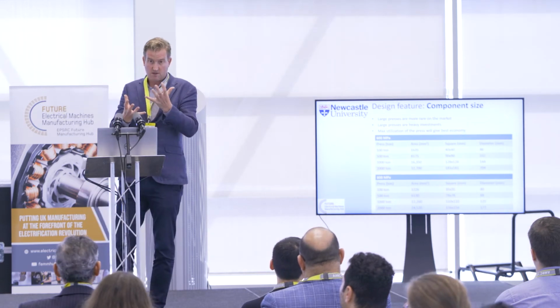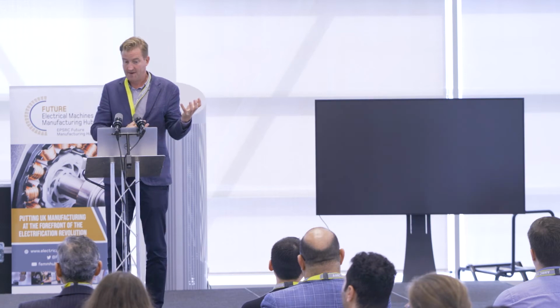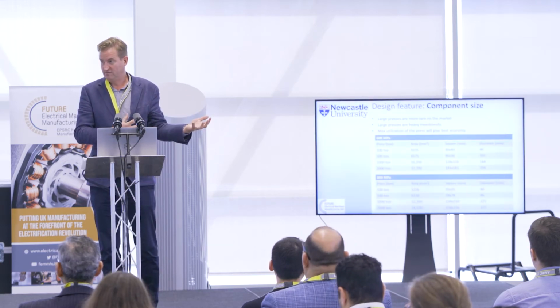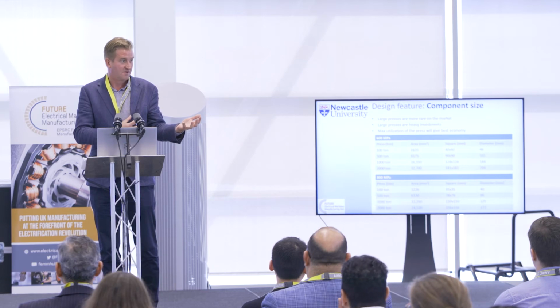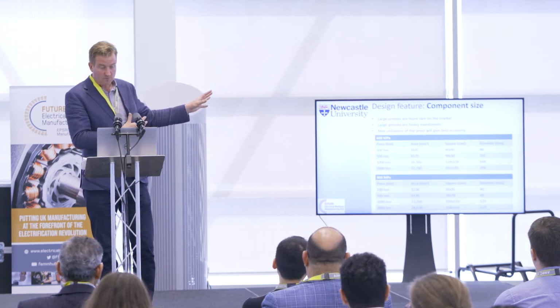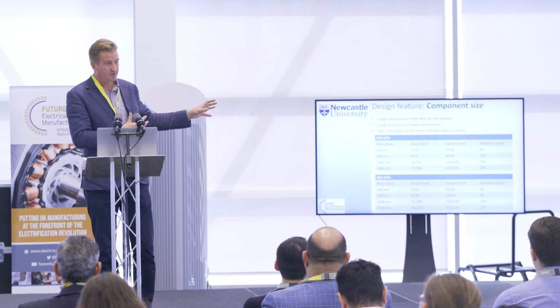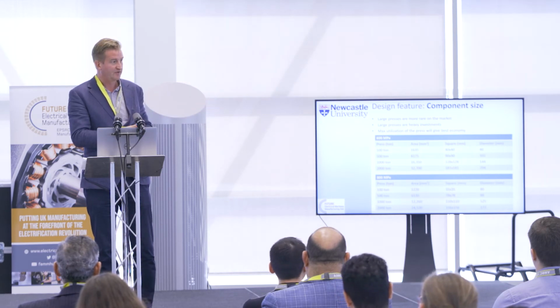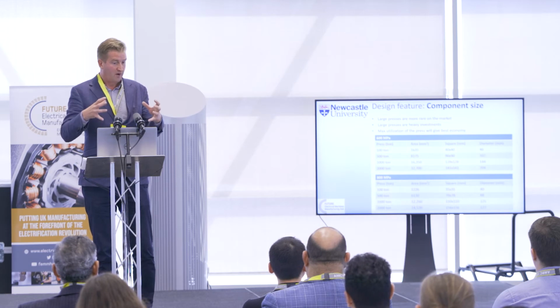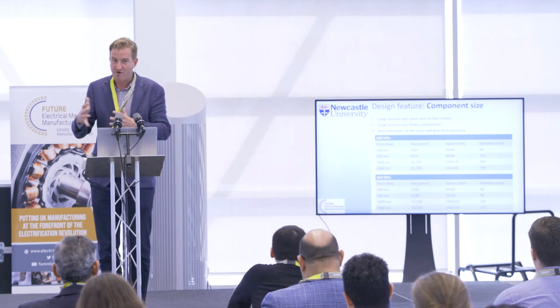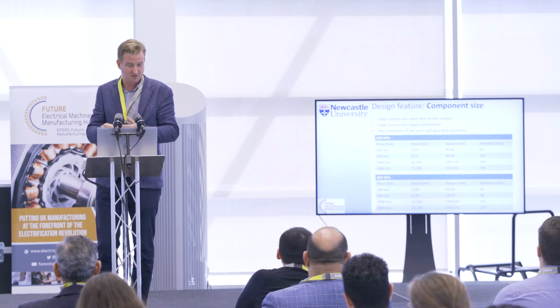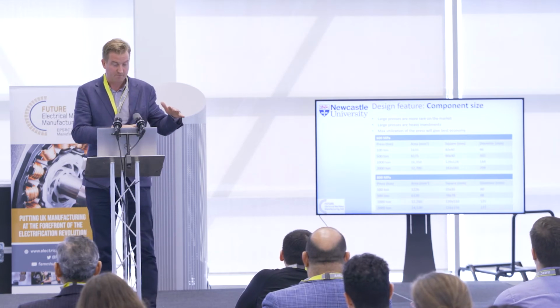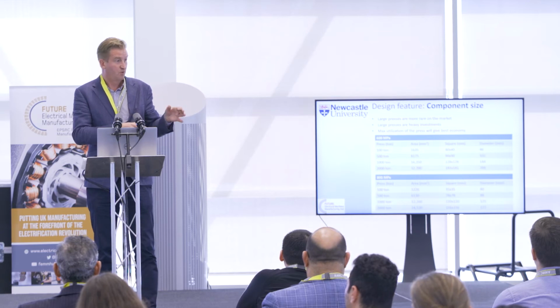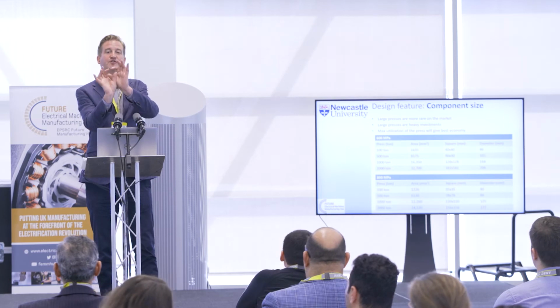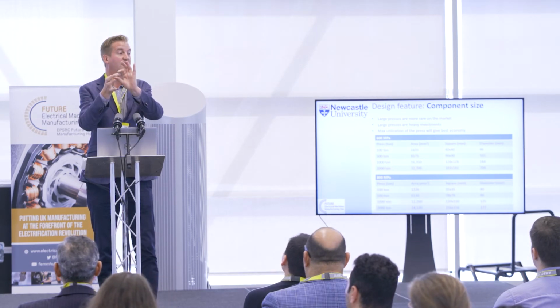So these components are pressed in a press of varying pressures depending on what we're doing. As a guide, we would want to press the component between 600 and 800 megapascals. So the size of the component and the size of the press is very important. Typically at 600 megapascals, the lower press pressure, a small 100-ton press would be able to compress a component that's about 40 by 40, so I guess a cube about that sort of size.